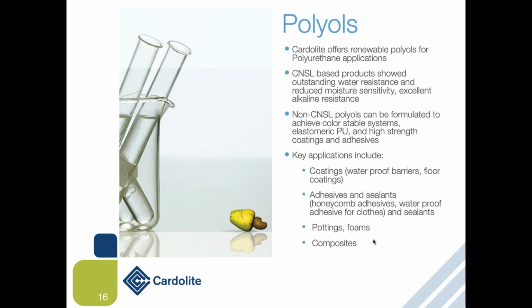So, based on what we have gone through, CNSL-based products typically show excellent water resistance and offer lower moisture sensitivity with excellent alkaline resistance, whereas some products that we have without CNSL tend to show color-stable systems, and can also offer elastomeric PU with high strength for coatings and adhesives. And the key application of these products has been, as I mentioned earlier, coatings and adhesives. You can also use them for potting and composites. Some of the polyols are also suitable for foam applications.